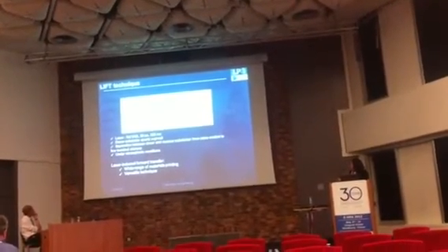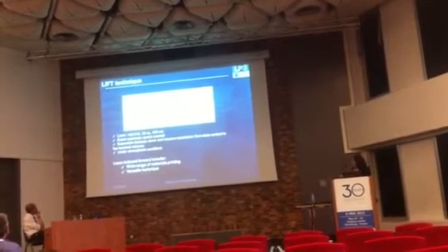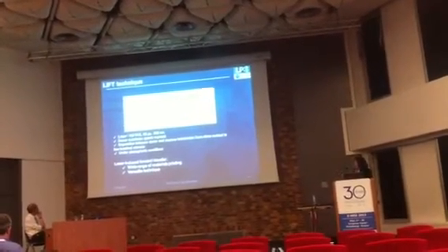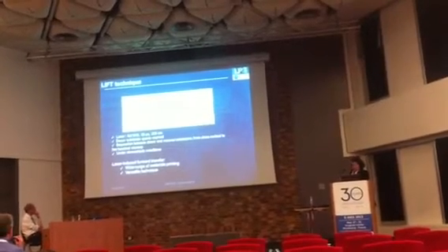So first, the LIFT technique. The main point is here. We have a donor substrate, which is transparent to the wavelength of our laser, and in close contact we place a receiver substrate. On the donor substrate, we prepare our layer of material, and with a single pulse we can transfer a pixel from the donor substrate to the receiver substrate.